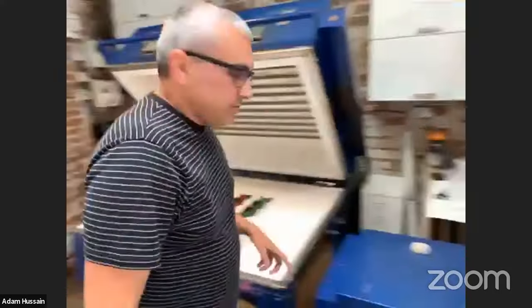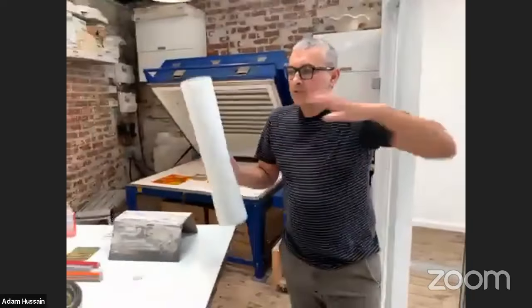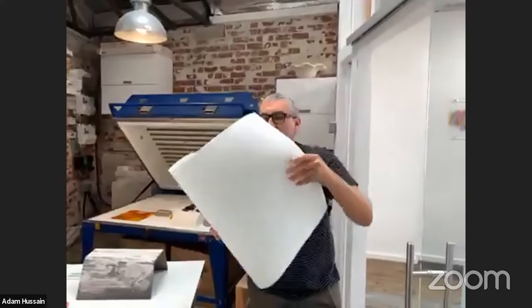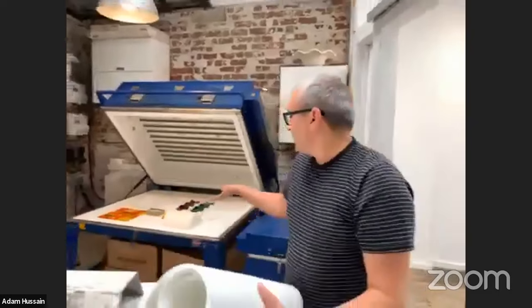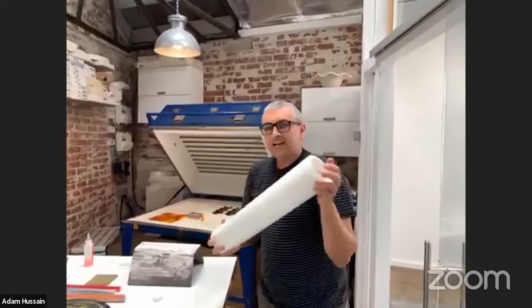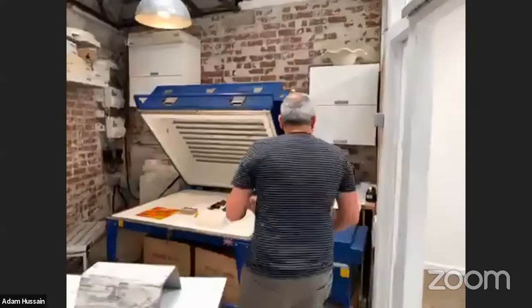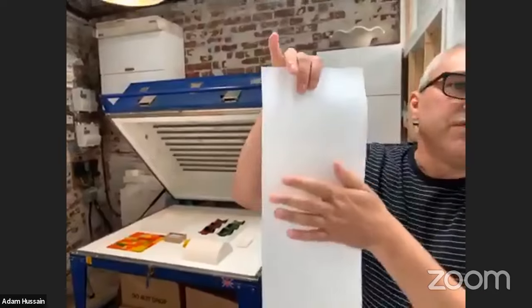What do you use underneath the glass when you fuse it? I use fibre paper — I line the kiln with three-millimetre fibre paper. The one-millimetre is too thin and sometimes you see the kiln bricks' texture taken on by the glass. If you want a finer finish on top of that, I then use Thinfire paper, which is also a Bullseye product, and that gives you a smoother finish on the underside of the glass.